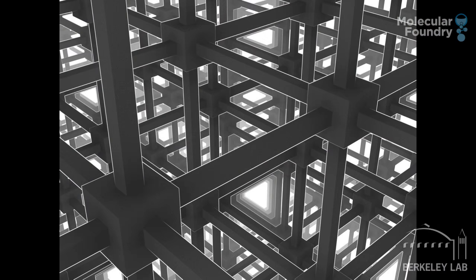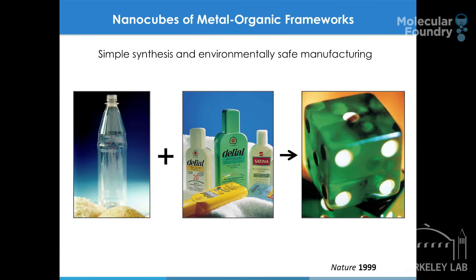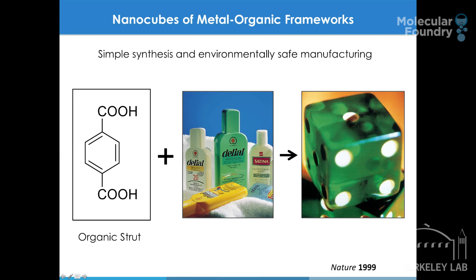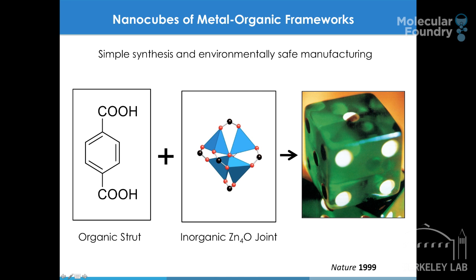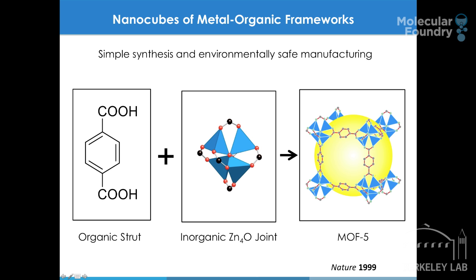So we set out to establish and develop this strategy to make three-dimensional structures that are based on the primitive cubic lattice. And here I'm showing a very nice rendering by Escher of the primitive cubic lattice. And here, from our point of view, this is constructed from six-way branching points that are linked together by what is called ditopic links. So as a chemist, this translates into terephthalate, a ditopic link, which is one of the main components of plastics, and zinc oxide, the main component of sunscreen, would serve as these multi-metal joints to make a variety of extended structures. In this case, a specific one that we targeted was MOF-5.